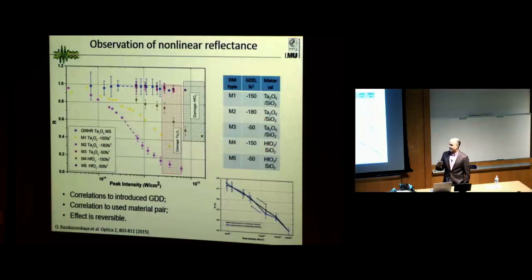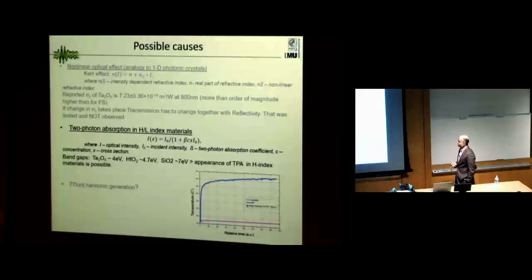Material which has higher nonlinearity, like tantalum, has a smaller band gap than the mirrors based on hafnium, because some mirrors almost don't show any of this effect and just get damaged. It means we started to look for the reason for such behavior, and actually the explanation is two-photon absorption, because the band gap of our material was not broad enough. In this particular case, we use a laser with 400 nanometers, and this 400 nanometers was exactly enough to get the two-photon absorption.